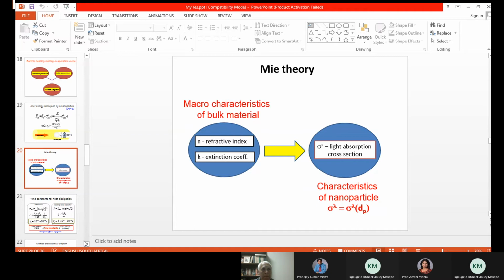Not so many people about 100 years before understood how excellent this result produced by Mie was, because at that time nobody thought about the nano size of the object. Normally the smallest size 100 years before was about a millimeter. Practically nobody operated with micrometer size at that time. But for several micrometers, if we produce a particle of 10 micrometers, for example, the absorption cross section will be very close already to the geometrical size of the particle.